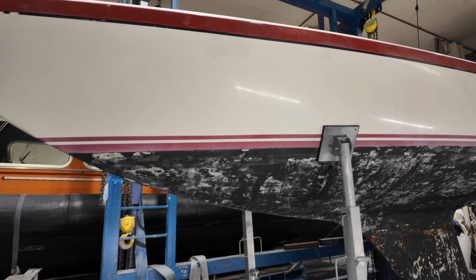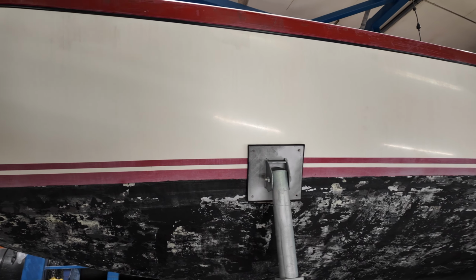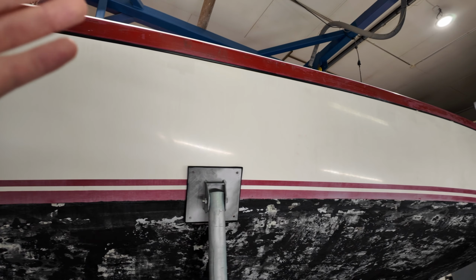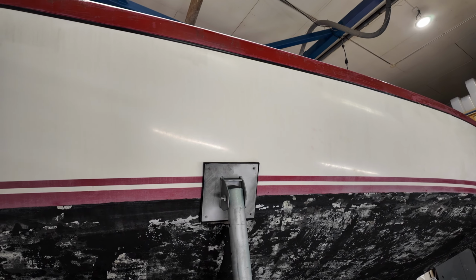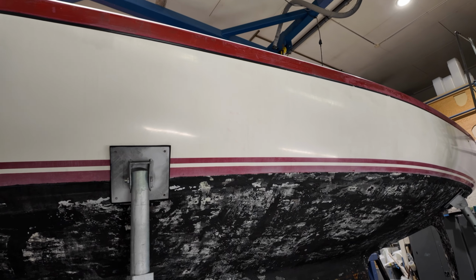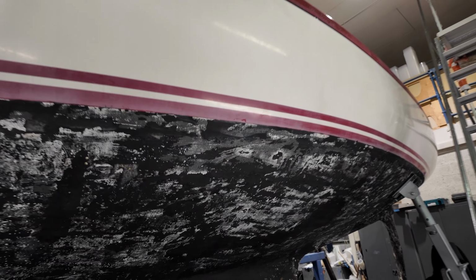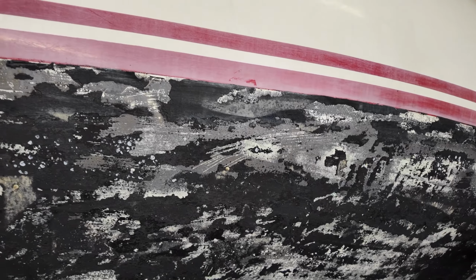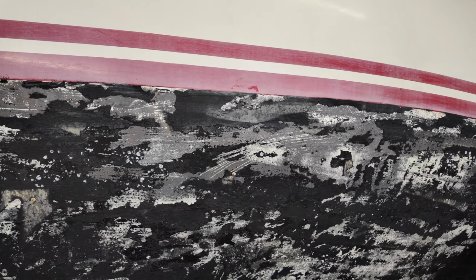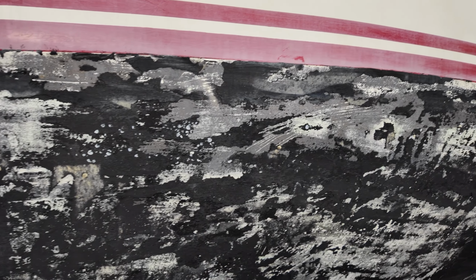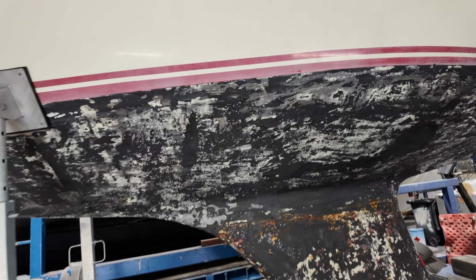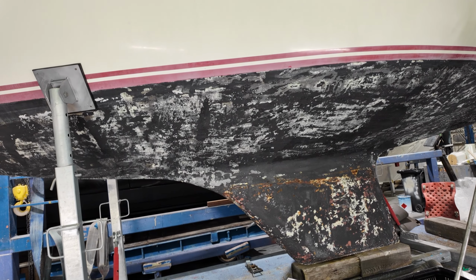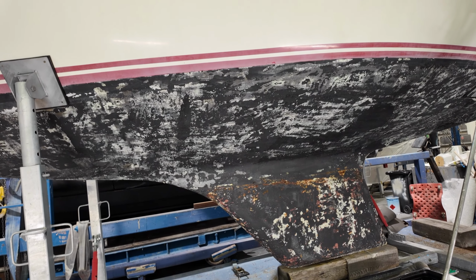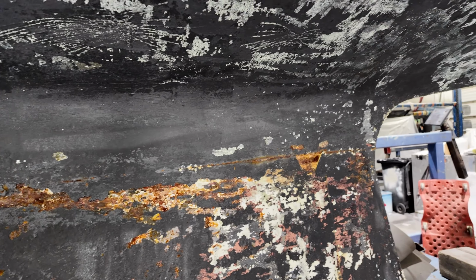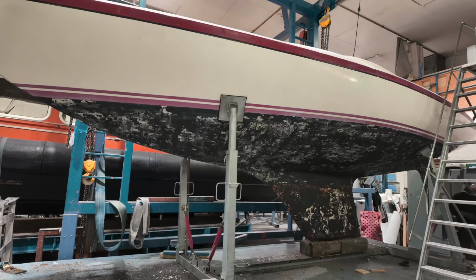The hull itself seems to be in quite a reasonable shape. There are a few scratches in the part of the hull above the waterline, and the paint job will have to be renewed, of course. I found some stress marks on the underwater part of the hull, but it's not such a big problem, I believe. The underwater paint will have to be, of course, scraped, sanded and applied new. I suspect that I will have to remove and reattach the keel because it looks quite rusty, and I found a few cracks in the bilge where the keel bolts are.